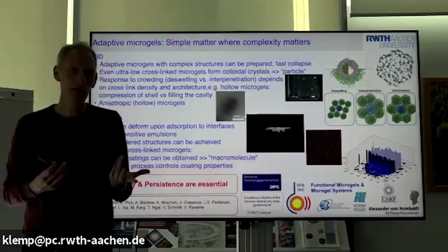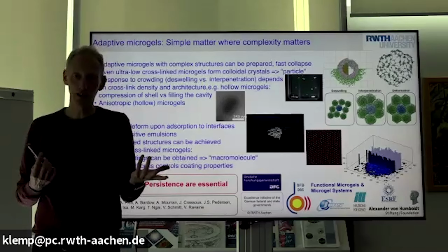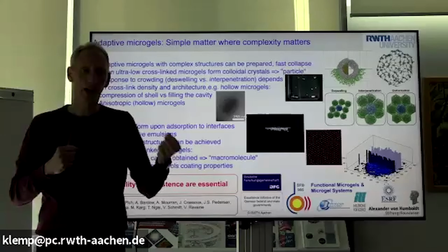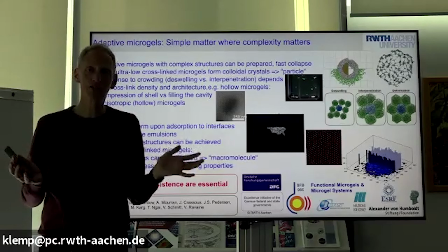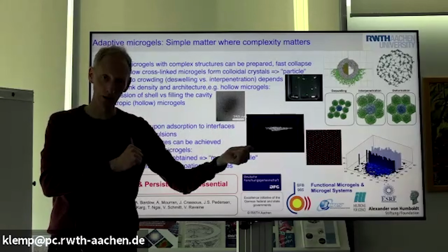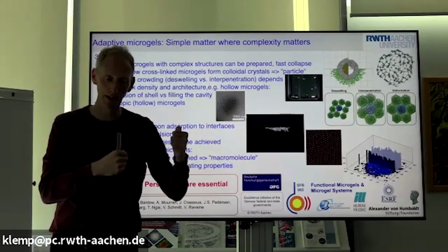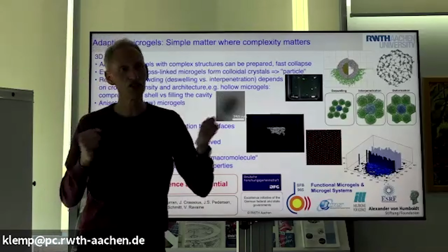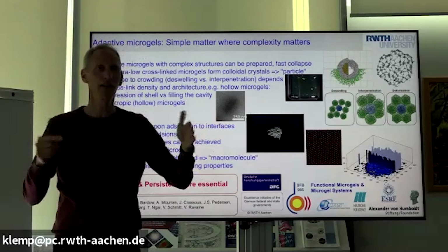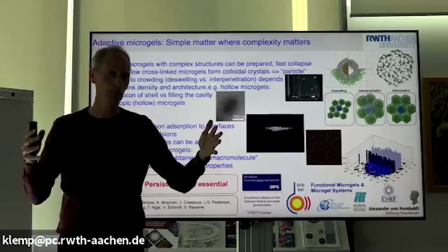for spherical objects, the viscosity depends on the volume fraction. When we change the temperature, we change the size and the volume fraction, and that perfectly fits to hard spheres until we get to dense packing. Beyond dense packing, it's different from hard spheres, obviously, because we can go to higher packing. Then the rheology is very rich, becomes also polymer-like, glassy-like, but in the dilute regime, up to 50% volume fraction, it behaves like hard spheres.